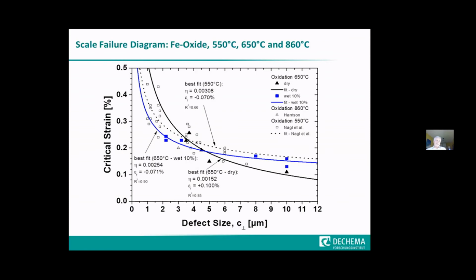And these values allow us to do a very conservative assessment at first to find out when we have to expect the first mechanical failure of these protective oxide scales, which does not automatically mean, as I said, that this is already the very beginning of corrosive attack underneath the oxide scale, because healing can prevent such attack. But it is, of course, already the first time in life that we have a critical situation where a material shows some Achilles heel, I would say.